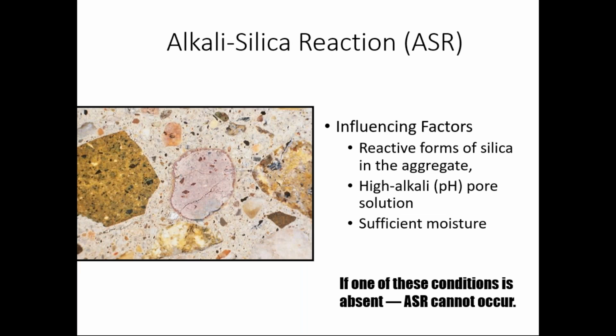What are the influencing factors? Reactive forms of silica present in the aggregate, which we will come to know only through petrography examination. High alkali pore solution is also responsible, and sufficient moisture. Sufficient moisture is present, then only alkali silica reaction can take place. If one of these conditions is absent, ASR will not occur. So all the 3 things.